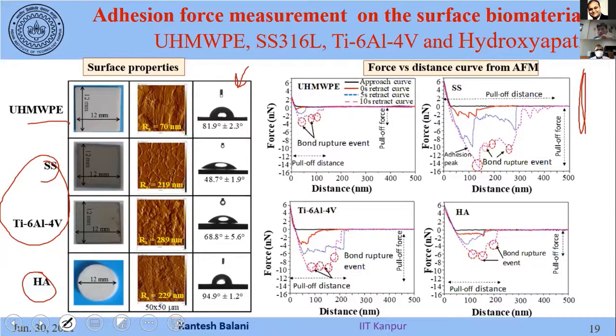Now there are 2 very important things to observe. First, for 0 seconds, you will see there is a small red curve, so the force required to detach it is much lower. And as I go to increasing dwell time, 10 seconds, this pink curve, the force values are actually much higher. Not only that, the distance or the interaction between the protein chain and the substrate also increases from 0 seconds to 10 seconds. That part you are able to appreciate. So distance is also increasing. You can see something here, right? Something like this here, here, and here. These are average curves, but you can still see they are more or less increasing, both in terms of distance and in terms of forces.